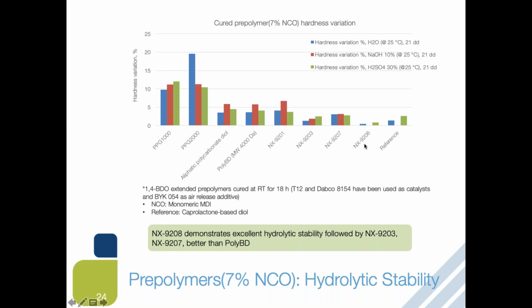As you can see, NX9208 showed the least change in hardness, meaning the best hydrolytic stability, followed by 9203, and then 9207. And as you know, poly-BD typically shows good performance in this regard as well. But as you can see, 9208 was the best.